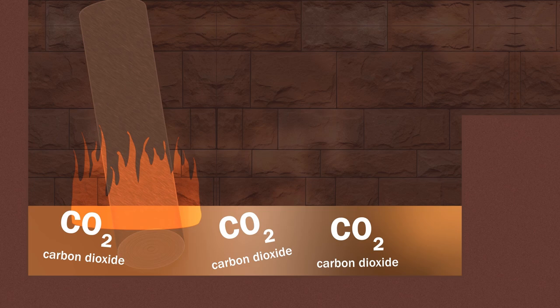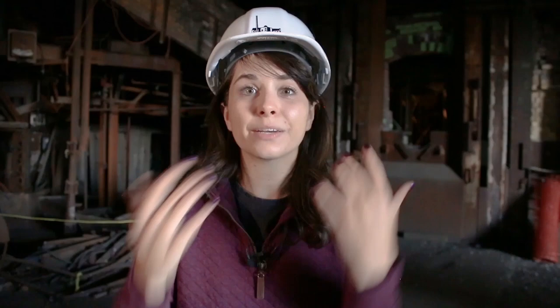The most interesting part of this process is something called rabbling. Workers would take an iron paddle called a rabble and mix up the molten metal to get some air into it. One goal was for that air to oxidize any impurities left in the metal, so they would separate from the bulk of the copper and could be skimmed off the surface. The trouble was, rabbling still left some excess oxygen in the mix, which could contaminate the metal or reduce its strength. To get that out, they took a green hardwood pole and dunked it into the molten copper — basically a tree. The pole caught fire immediately, since copper doesn't melt until it reaches nearly 2,000 degrees Fahrenheit. When the pole caught fire, it released a bunch of carbon. That carbon reacted with any excess oxygen left in the mix to form carbon dioxide gas, which then left the copper bath and floated out of the furnace. It was such a clever idea.